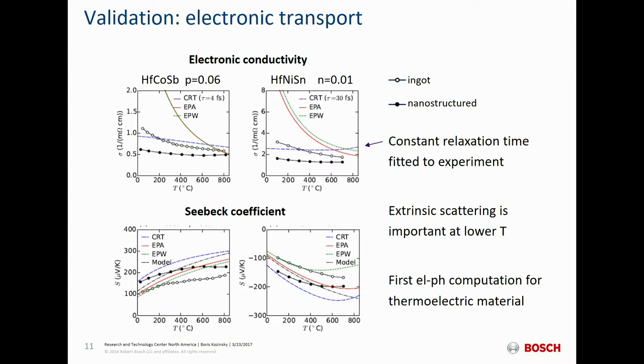We wanted to check how well this method does relative to the fully exact interpolated momentum-space integral. It turns out to be okay, which is a bit surprising — we still don't fully understand the limits of this approximation. Looking at electronic conductivity for these materials and comparing EPW (the Wannier-interpolated momentum-space integration scheme) with EPA (this averaged energy scheme we developed), it does very well, especially at higher temperatures compared to experiment, which means we're capturing the correct phonon scattering that dominates at high temperatures. We do poorly at low temperatures because defects dominate scattering there, which is expected. For the Seebeck coefficient, results are already in good agreement because the lifetime is not a very important factor for Seebeck.